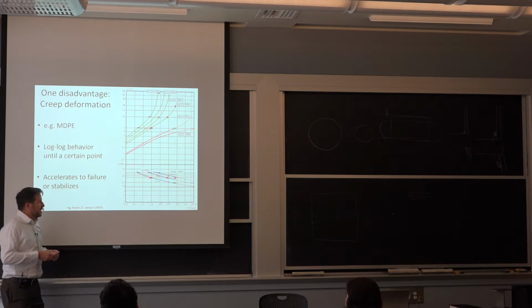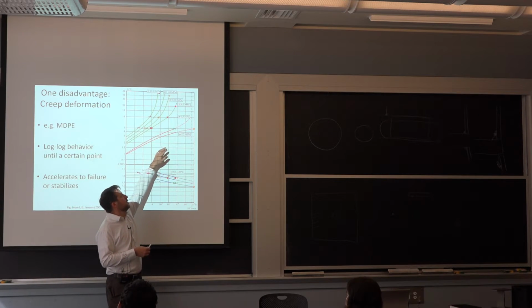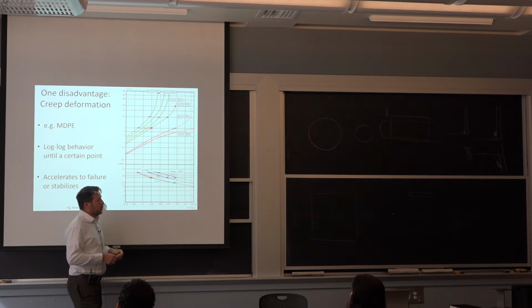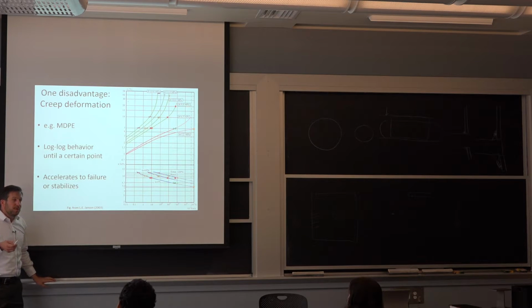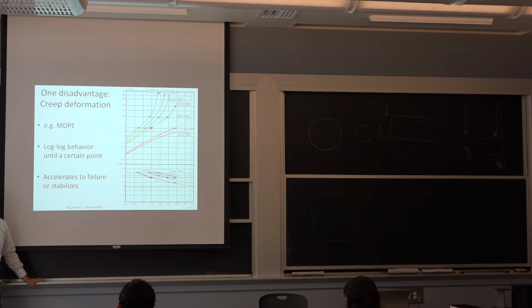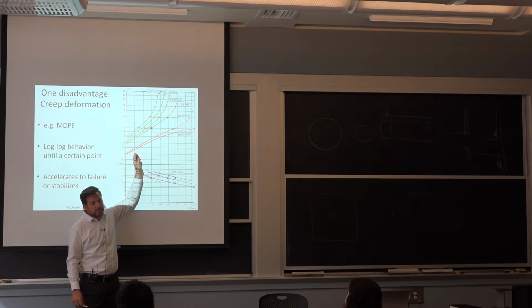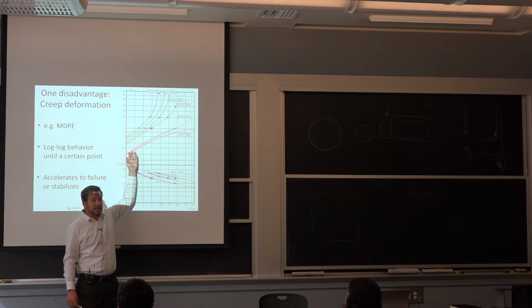Because you have these two different behaviors, we won't go into the details of that, but when people talk about time temperature equivalence, there is something to be said with the polymer that if you give it more time to deform, that may be the equivalent of more stress. That's a little bit what the principle says. But that is so long as your acceleration factor by putting more stress doesn't change your failure mode. And in this case, it does.